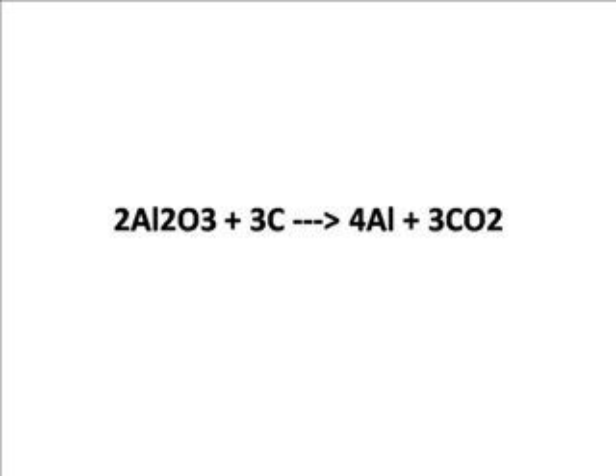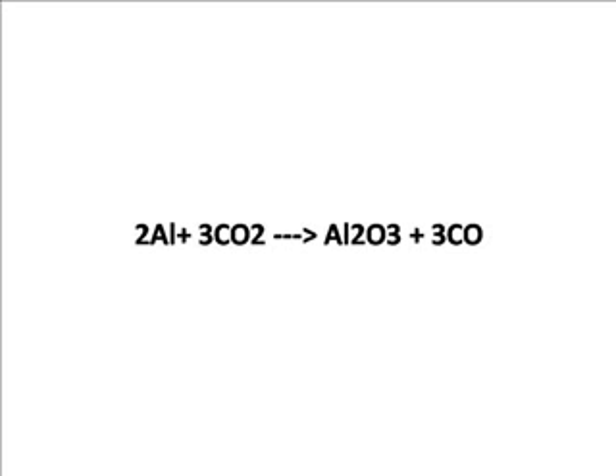Oxygen is produced at the graphite anode and will react with the carbon to produce carbon dioxide, as you can see in this equation. However, some of the metal, instead of being deposited at the bottom of the cell, is dissolved into the electrolyte and reoxidized by the CO2 that has evolved at the anode. You can see that in this equation. The reaction can reduce the efficiency of the cell and increase the cell's carbon consumption.